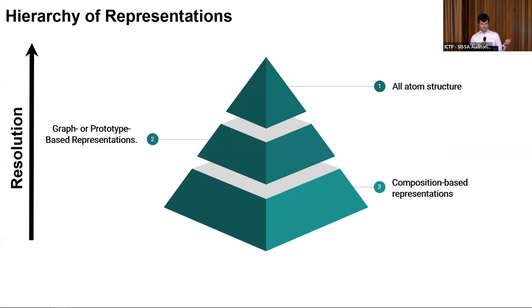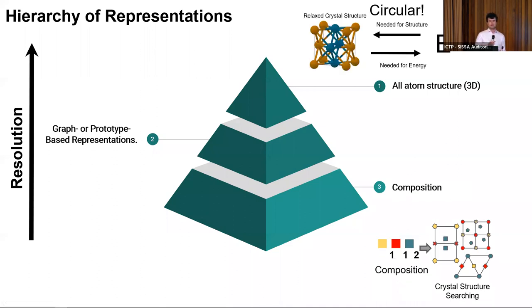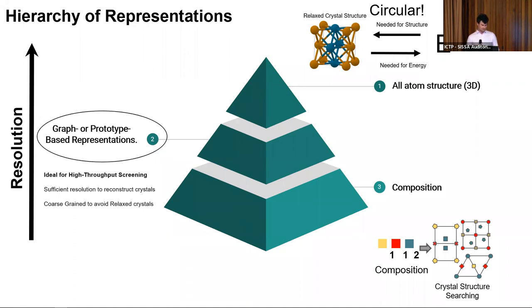To reiterate: coordinate-based representations are not unique, making them unsuitable, and full structure-based representations suffer from the circular problem that you need the relaxed structure to predict energies. What you want is something like a graph or prototype-based representation. However, there has not been much work on this in literature.